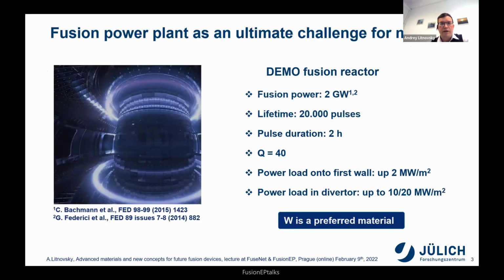So speaking about the fusion power plant, this will be a fusion device with unprecedented power parameters. The fusion power will reach 2 gigawatts. For lifetime, it will still be pulsed and arranged for 20,000 pulses, but with a pulse duration of 2 hours. It is really quasi-stationary with a fusion gain of 40, and will feature a power load on the first wall of up to 2 megawatts per square meter, while the power load in the divertor can reach 20 megawatts per square meter. And under these conditions, the materials facing the plasma, you can see these materials at the walls of the vacuum vessel and in the lower part in the divertor.